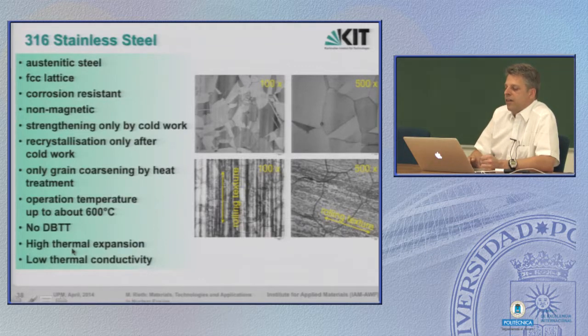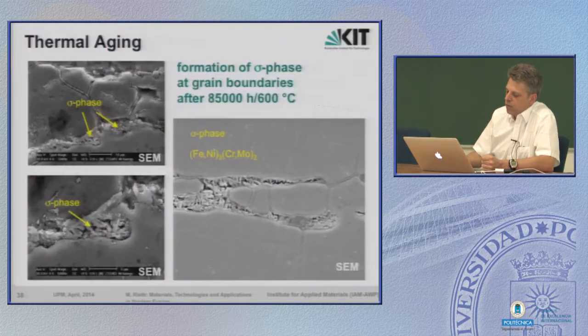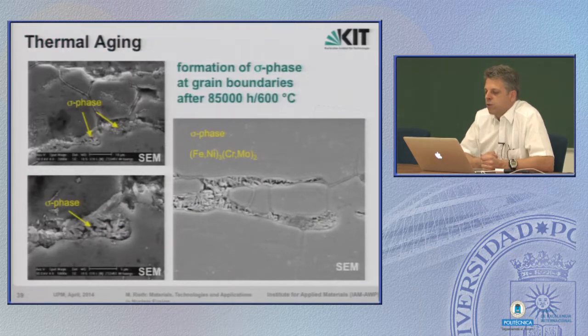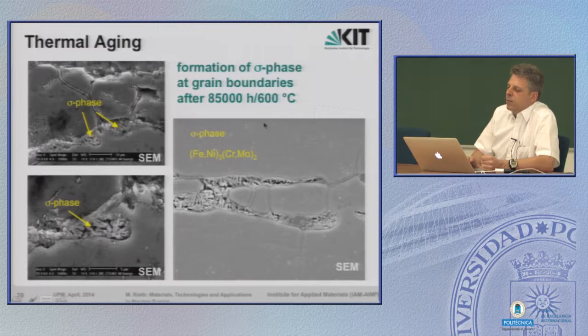Drawbacks are the high thermal expansion and the low thermal conductivity. There is one other drawback which you should keep in mind if you ever want to use 316 steels at higher temperatures or for high temperature application. They are very prone to what we call thermal aging. And this is the effect on the microstructure, for example, after 85,000 hours at 600 C.